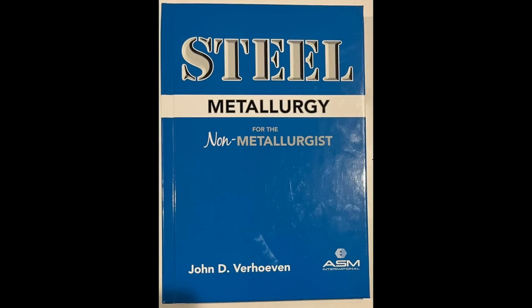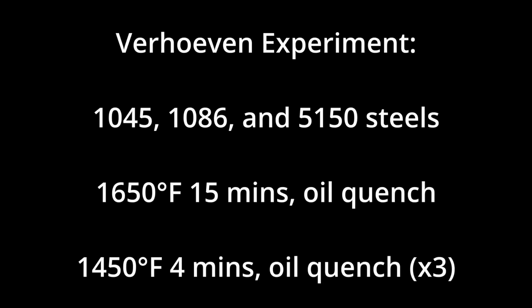Another prior experiment that is related to what we're talking about here is from Dr. John Verhoeven in his book Steel Metallurgy for the Non-Metallurgist. He wrote that for knife makers and bladesmiths several years back. And he also did a triple quench experiment with salt baths. He did it with 1045, 1086, and 5150 low alloy steels. The first thing he did is he heated the steels to 1650 Fahrenheit for 15 minutes and quenched. Then he measured the grain size. Then he heated each steel to 1450 for 4 minutes each in a salt pot. And he quenched, and he did that 3 times. And then he measured the grain size again.